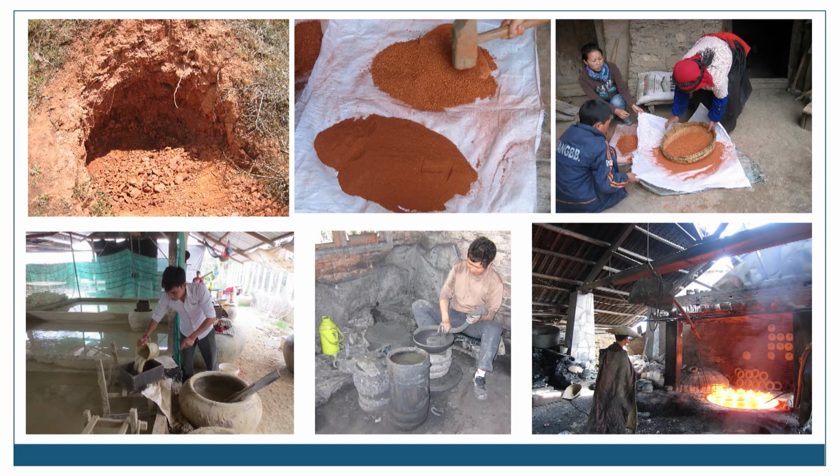While a lot of effort has gone into developing analytical methods for studying ceramic materials, in contrast, very little consideration has been given to pore systems and what they can tell us about ceramic production and use. And yet, the structure of a pore system is strongly related to the raw material selection, processing, and fabrication methods, and firing regimes. So characterizing pore systems can help in identifying groups of similar related ceramics and for determining how well they might have functioned for particular uses.